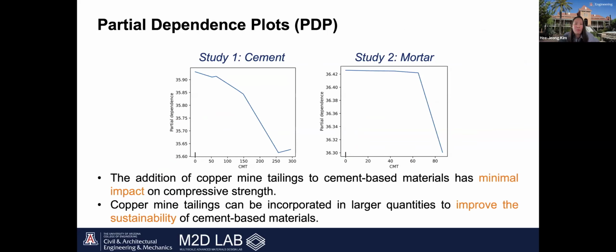And to see how copper mine tailings affect compressive strength, we used PDPs. In study 1, adding up to 250 kilograms per cubic meter of copper mine tailings caused only a small decrease in compressive strength. In study 2, adding up to 80 kilograms per cubic meter of copper mine tailings reduced compressive strength by just 0.12 megapascal. These results show that we can incorporate a significant amount of copper waste to produce sustainable construction materials with a minimal loss in strength.